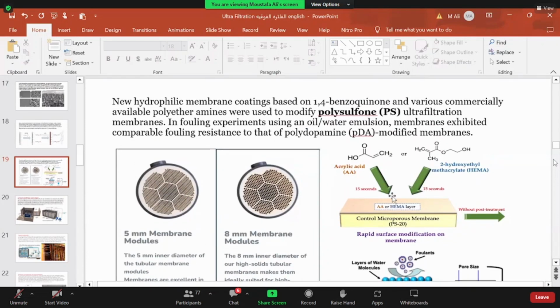technique, which is plasma vapor absorption technique, using, for example, here we use two materials, which are acrylic acid and 2-hydroxy ethyl methacrylate. So both of the two materials can form, as I said, a layer over the membrane surface to give it special characteristics.